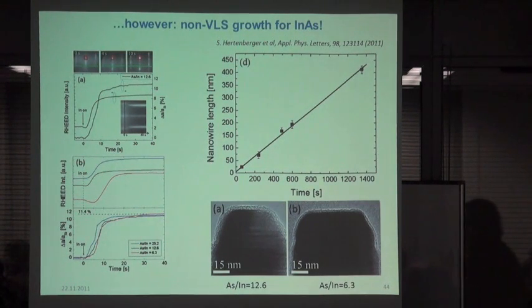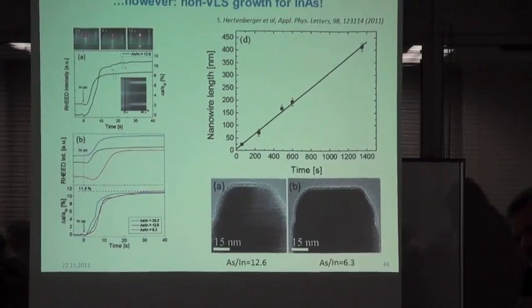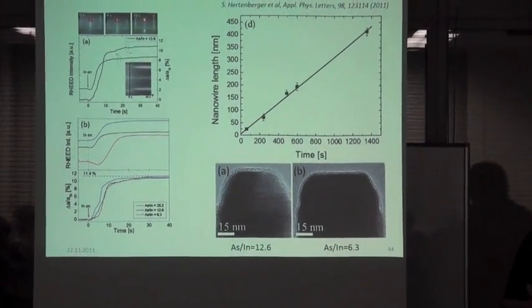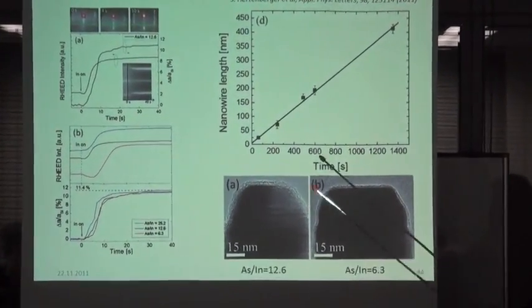Now, indium arsenide is not vapor liquid solid growth. So for materials people, this is quite surprising. There are people who claim you cannot grow wires without vapor liquid solid growth. I think this is vapor solid growth. We have several, let's say, evidence for this. First of all, we never see a droplet, but this can be evaporated before you really measure it. So this is not the proof.